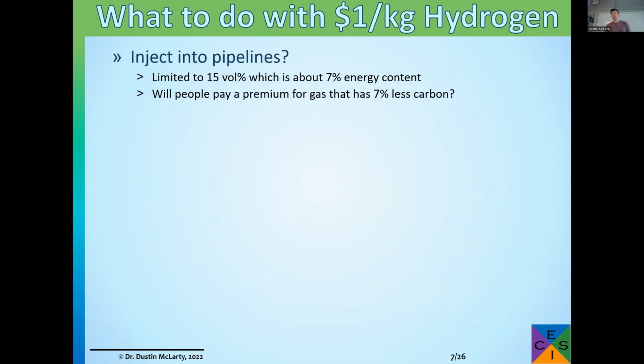So imagine we are successful in producing $1 per kilogram hydrogen. What are we going to do with it? Well, there's a lot of talk, especially in our region, about injecting it into the pipeline, decarbonizing that natural gas system. Realistically, upper limits are about 20%. They're targeting maybe a 10% regulatory maximum initially, but let's average that and say we could get up to about 15% of the volume in our natural gas system as hydrogen. Unfortunately, that only works out to about 7% of the energy content, since hydrogen is a rather not dense gas.